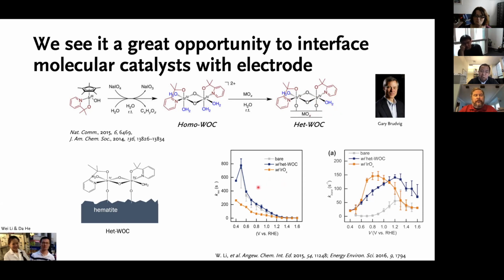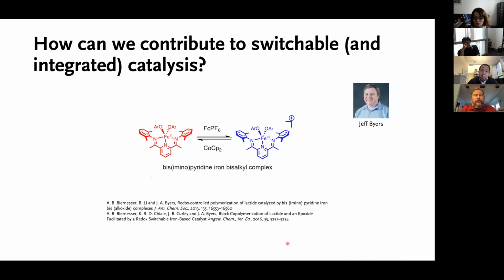But in this particular study, what we have proven was that when we have this molecular catalyst on the surface of iron oxide, it helps charge transfer, but it does very little in terms of charge recombination. And that's the key point of this study. But the connection to the center is now already established. It is at this point in time that nice work done by my colleague, Jeff Byers here at BC, caught our attention.